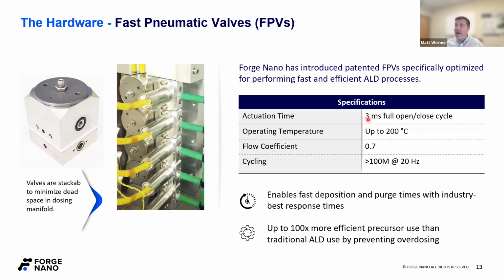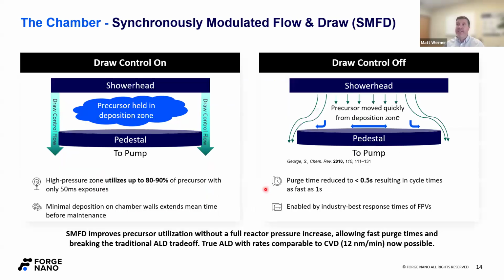We've tested this quite often in our lab. It's quite fun because you get really fine control over the number of molecules that you're putting in the chamber. It's pretty cool. And they're primarily stainless steel, so they're good up to 200 C. We've been running these for years, so we know they're stable. So these really work in tandem with the reactor design.